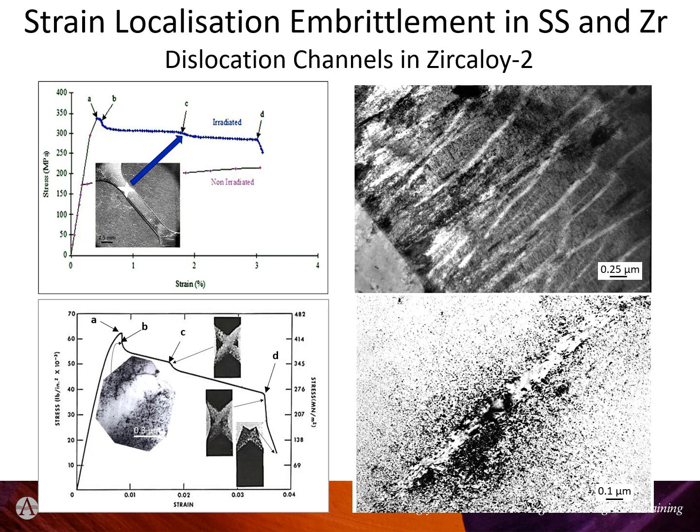When you have an irradiated material and you test it, what is generally observed is a load drop at a certain point. You'll strain the material elastically until, here's a non-irradiated case compared to the irradiated, you elevate the yield point. There's also the UTS relative to the unirradiated case. But when the material eventually does yield, it does so with a yield drop, and then in effect what we have is softening. The material is much easier to deform after this point.